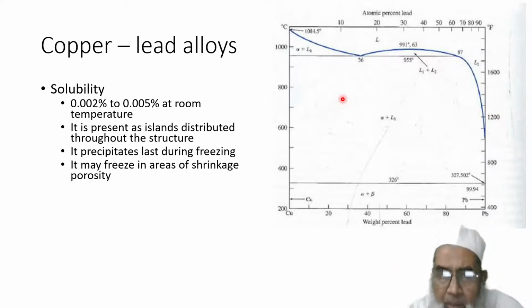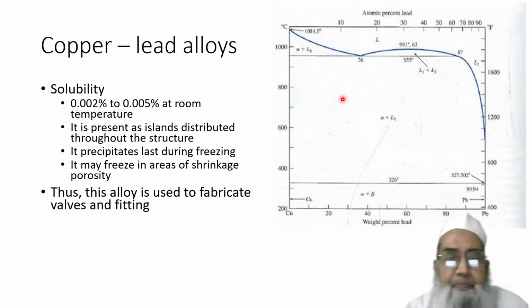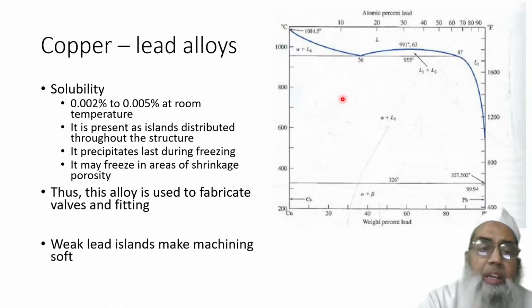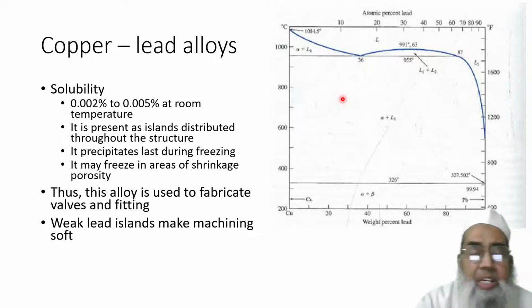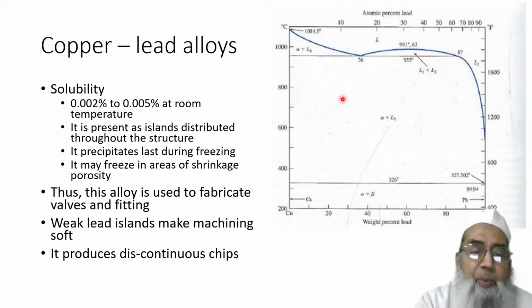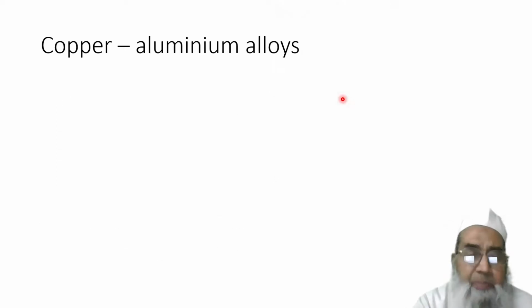While freezing, they precipitate out as islands in the areas where the shrinkage process takes place. If the amount of lead is more, then this of course enhances machinability, but obstructs the appearance of it. Thus, the alloy is used to fabricate valves and fittings. Now, weak lead islands make machining soft, but it produces a discontinuous chip.